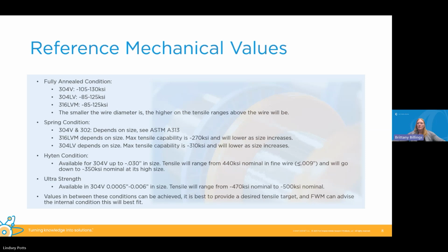Moving down to our spring condition, these are also dependent on the size. For 304V and 302, we're going to reference ASTM on those, and those will go along with those values. For 316 LVM, the max tensile capability is going to be about 270, and then will lower as it increases. And for 304 LV, the max is going to be about 310, and that will also lower as the size